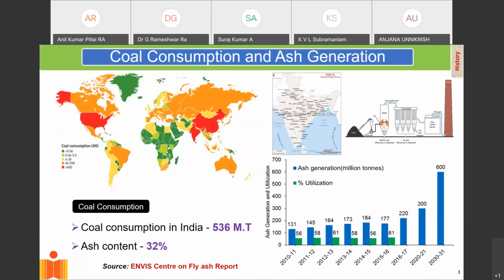Now, the problem we have is the gap between the production and the consumption. If you look at the graph here, the blue lines indicate the production of fly ash, including the expected production of fly ash. The green bars show the consumption of fly ash. So we are even today lagging behind in the consumption. Even today, our consumption of fly ash is around 60–65%. The remaining part of the fly ash is remaining unutilized.